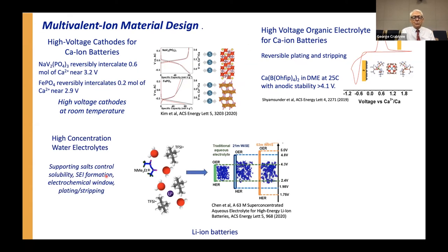And when it comes to zinc, it's really a question of the water electrolyte. That's the cheapest one. And remarkably, looking at a lithium battery here, but in concentrated water electrolytes, this happens to be lithium TFSI, and a separate cation, this organic cation, which is put in as a supporting salt, which does two things. For one thing, it doubles the solubility of lithium TFSI, so suddenly you can get a lot more in. And it raises, as this diagram shows, the voltage window for electrolysis. It goes from 1.23 to 3.25 volts. So you get a much higher operating range.